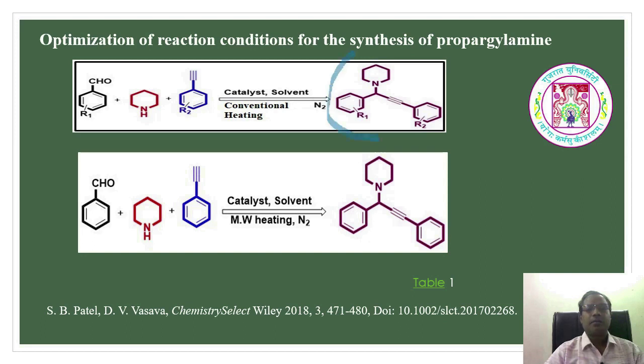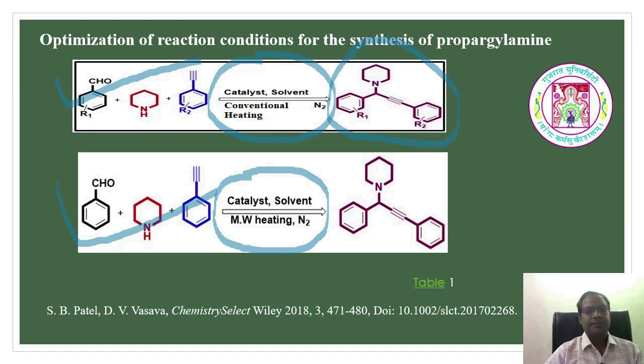Now here it is the synthesis of the propargylamine. This method is the conventional method, whereas this method is reported by us. In the conventional method, different metal catalysts are utilized. In this we have utilized silver nanoparticles doped on the graphitic carbon nitride. In the conventional method, around 120 degrees Celsius temperature is reported, whereas during optimization of the reaction, it was reported at 80 degrees Celsius.